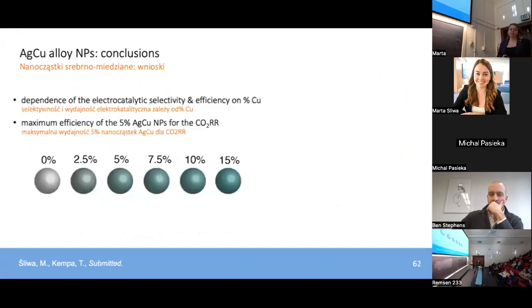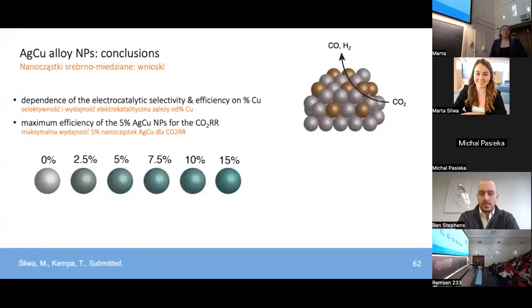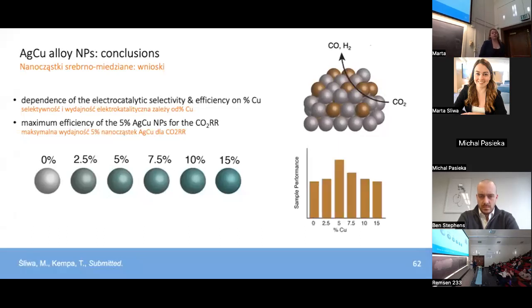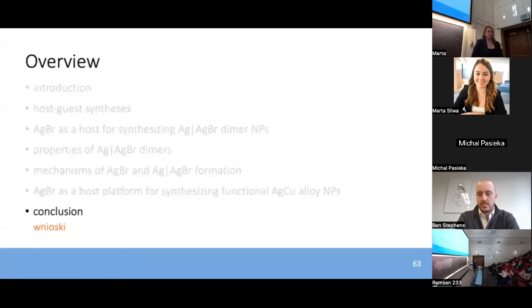So to conclude this section, we synthesized, again, dilute copper and silver alloy nanoparticles across a 0 to 15% nominal loading composition range by way of that silver bromide host. We investigated how we could use these particles for the electrocatalytic reduction of CO2. We also investigated their activity as a function of the copper percentage and found that the 5% copper sample is the best performing catalyst in our system.